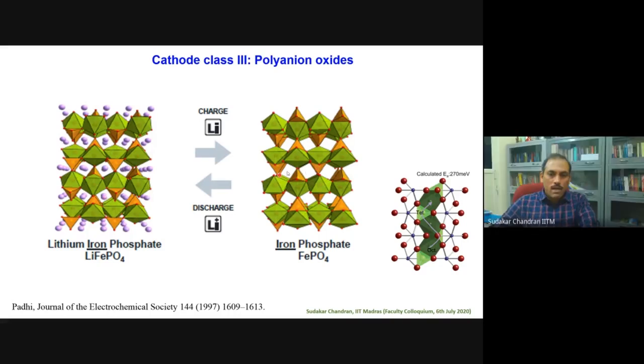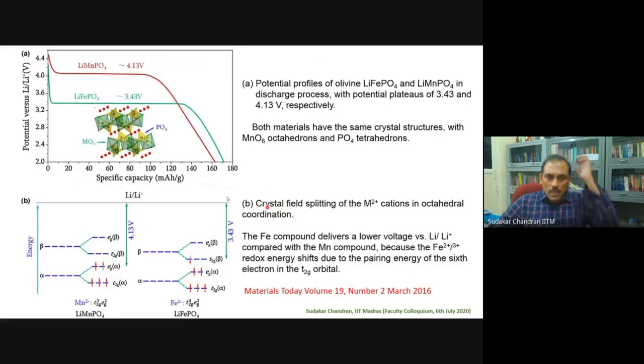There are tunnels running along the b-axis, and lithium moves in and out through these tunnels. Of course, it doesn't go straight. People have shown theoretically that the position it takes goes in a wavy pattern through the channels. And this particular compound, LiMnPO4, also was prepared, and it was shown to have much higher voltage than LiFePO4, but the capacity is more or less equal.